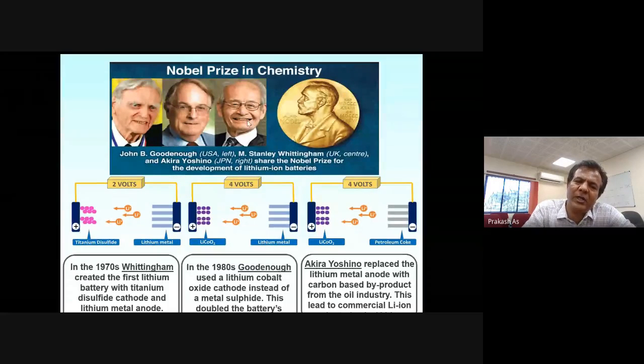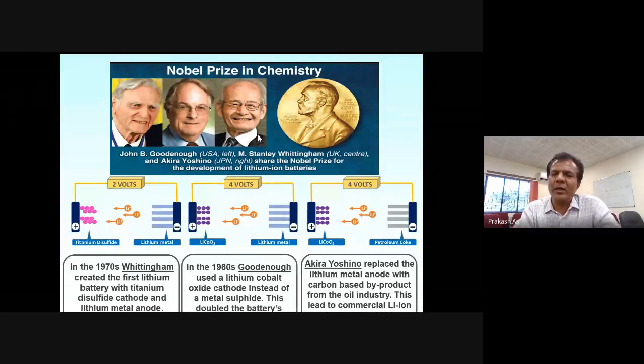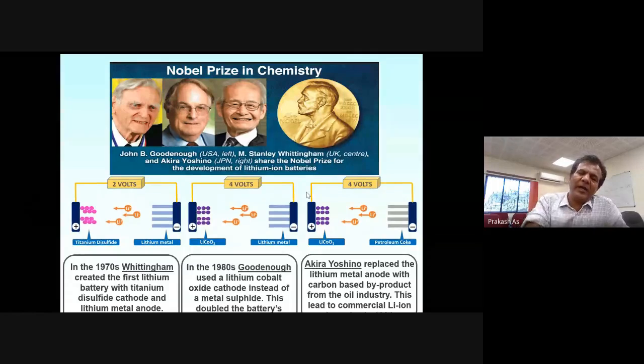Then Professor Akira Yoshino, a Japanese scientist in the petrochemical industry, was working on different kinds of carbons, some disordered carbons. What he did was use graphite. Graphite is a layered material. So he used a graphite-based carbon. First he used a petroleum pitch carbon, and then he demonstrated lithium intercalation into these graphitic layers. Therefore, now you don't need to use lithium metal. You can just use graphite. When you charge it, lithium ions from lithium cobalt oxide are intercalated into the graphite, and you see a voltage across. So practically, these things became possible.